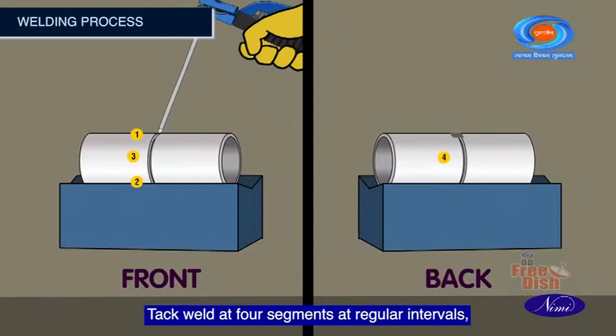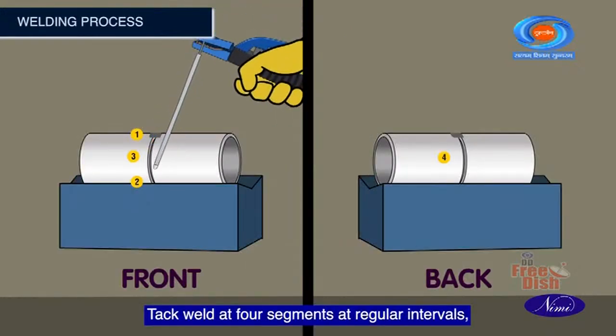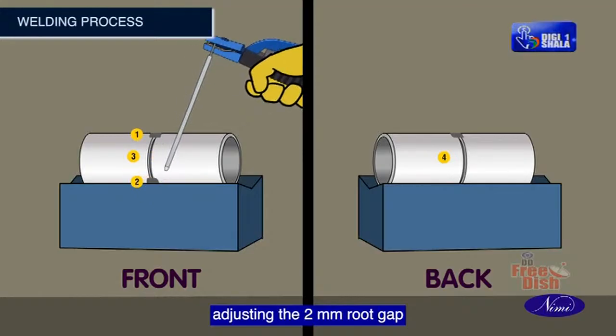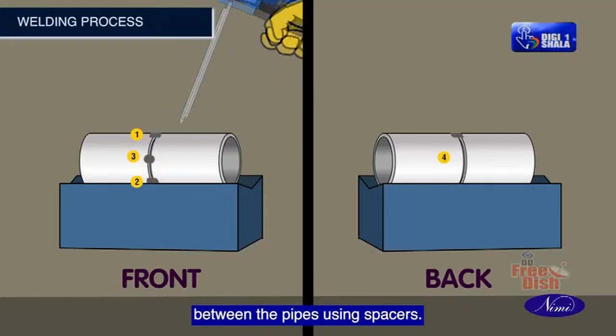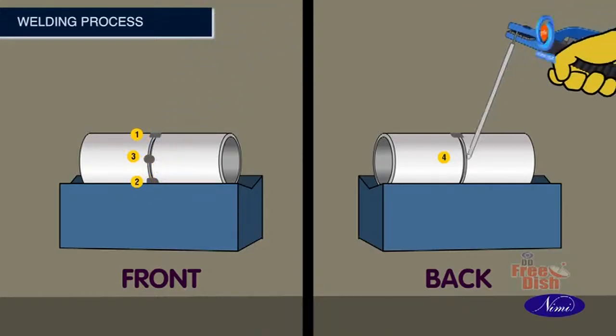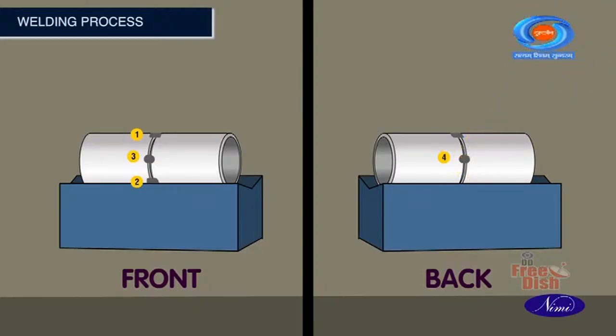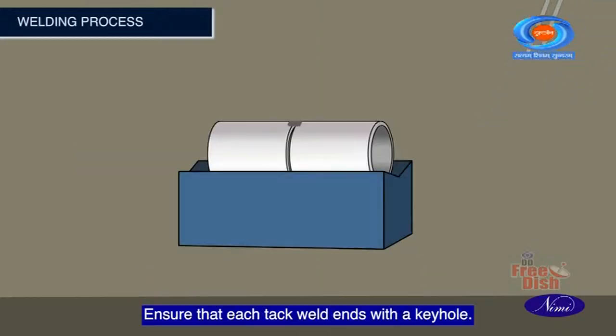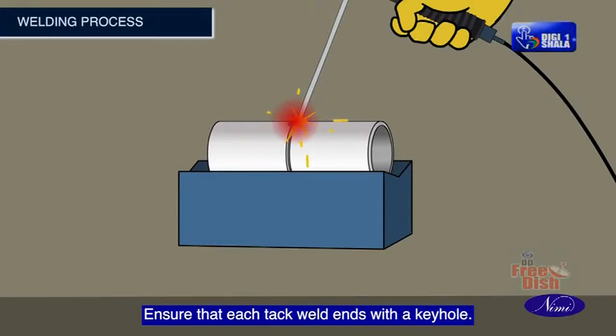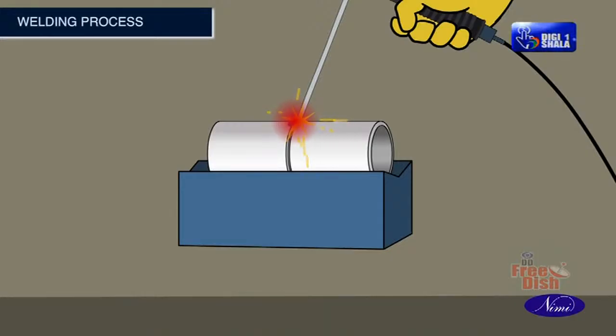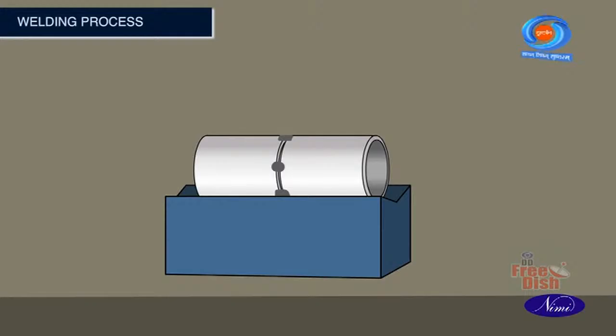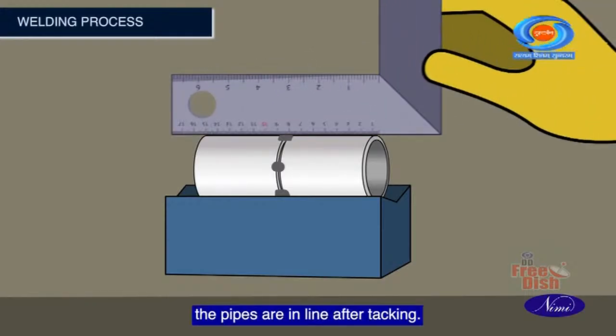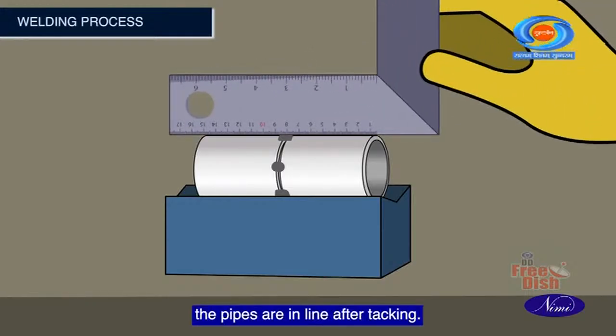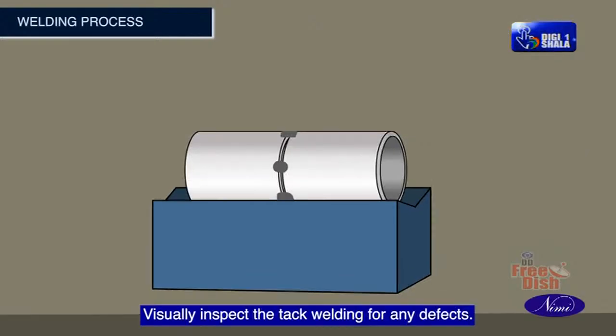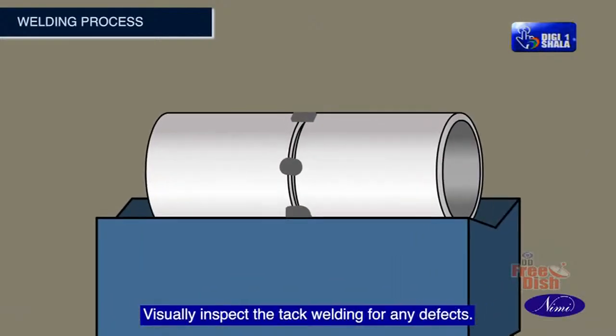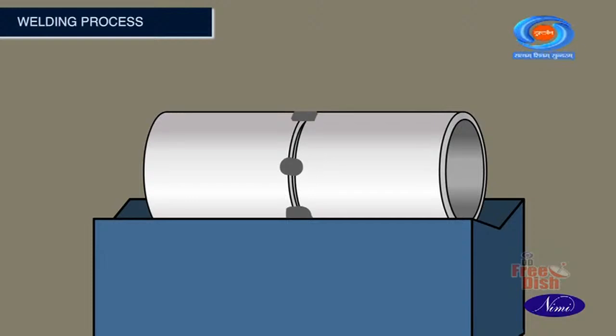Tack weld at 4 segments at regular intervals, adjusting the 2 mm root gap between the pipes using spacers. Ensure that each tack weld ends with a keyhole. Use a tri-square to check that the pipes are in line after tacking. Visually inspect the tack welding for any defects.